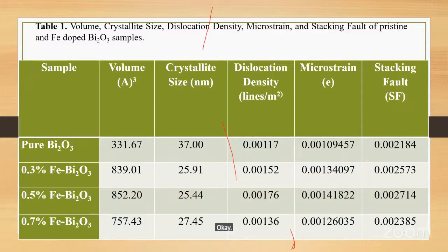Okay, now you see, and from this one can understand that the crystallite size goes on reducing and volume enhances if the concentration increases. The volume here, you see, is enhanced up to 0.5 and then suppressed. Similarly, again you see the crystallite size decreased, whereas the dislocation density enhanced.